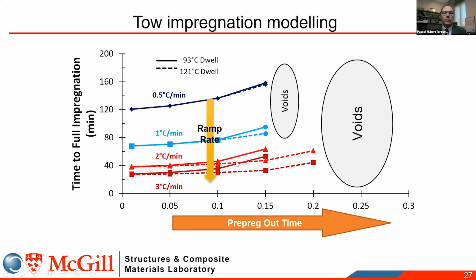And then you can see that by changing the heating rate during the cure, you can make the impregnation more efficient. And also you can have a little bit more robust system where you can tolerate a little bit more out-time problems. So this kind of insight through the micro-CT led to a better understanding of the process, and therefore that could be used back in production to guide what kind of manufacturing protocols could lead to problems.